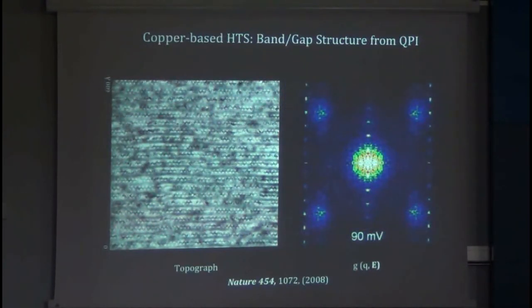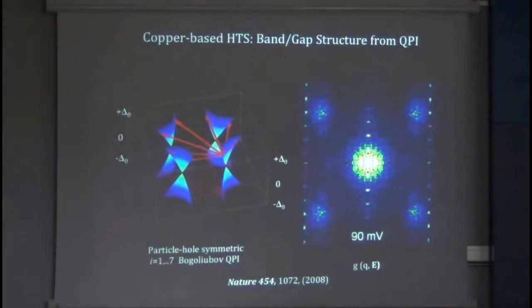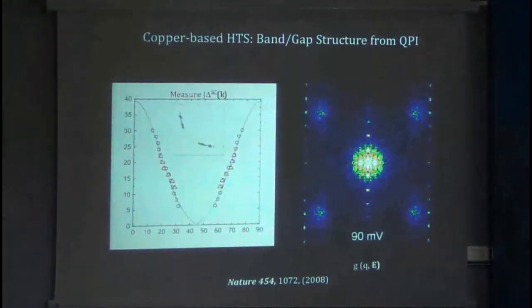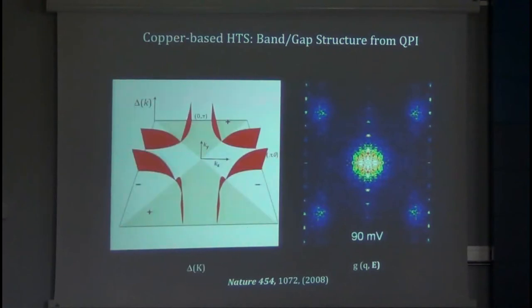And last but not least, we can use this Fourier transform STM and a model of the d-wave energy gap structure. We can predict each of the scattering interference wave vectors, extract where the Fermi surface was and what the shape of the gap is, and we come up with a nice nodal d-wave superconducting energy gap. Photoemission colleagues indeed found this at least a decade before we did.